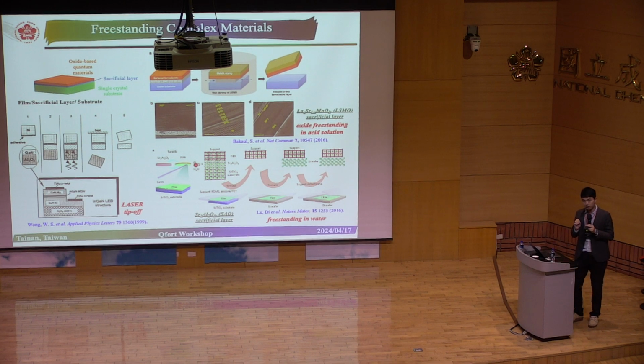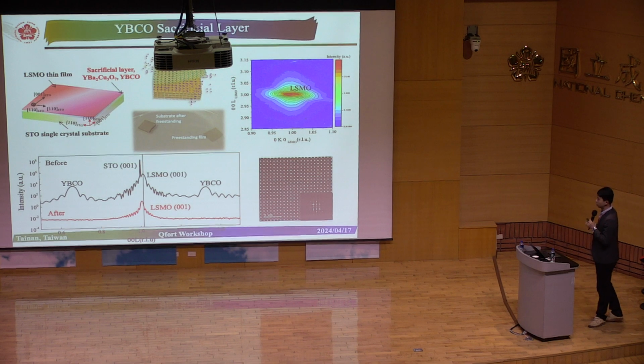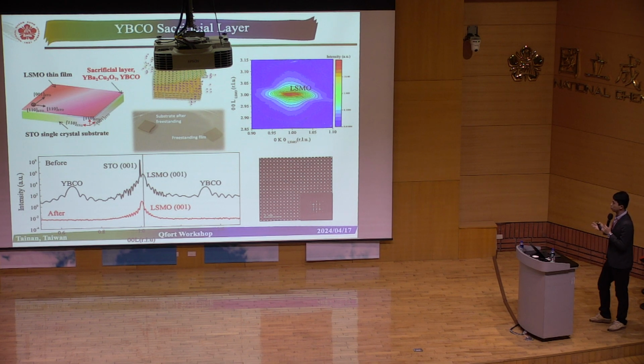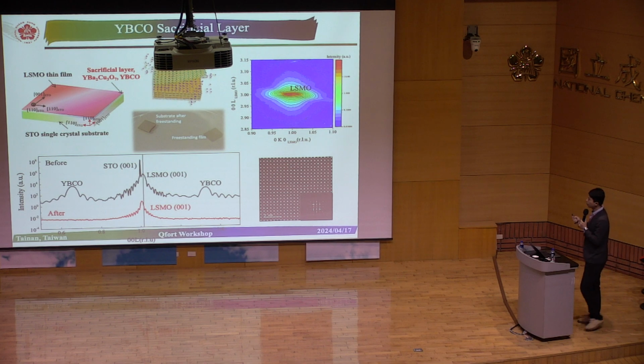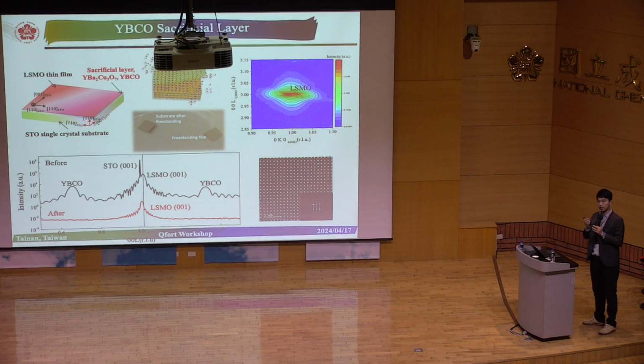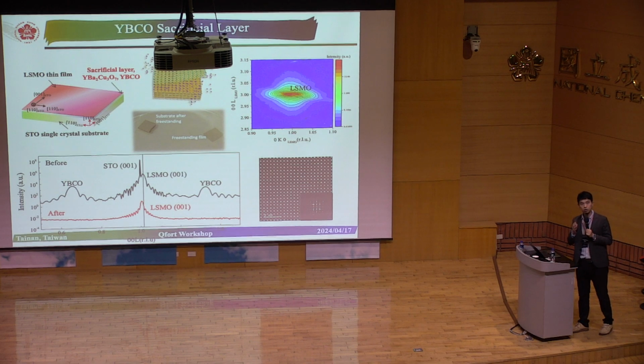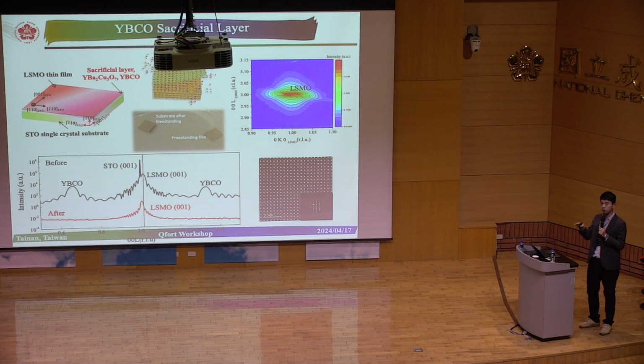So we started to ask ourselves whether we can develop a new material which enables us to get a faster freestanding thin film. To get the whole process done as soon as possible. Then we came back to, we occasionally found a classic material, the classic high temperature superconductor, YBCO. We found that this material can be easily dissolved in water or a very light acid.